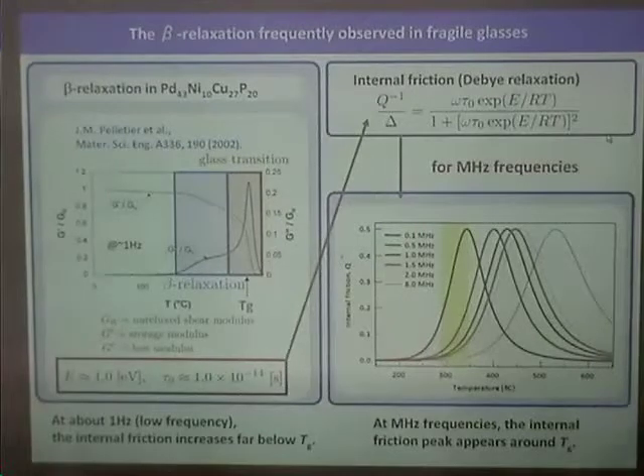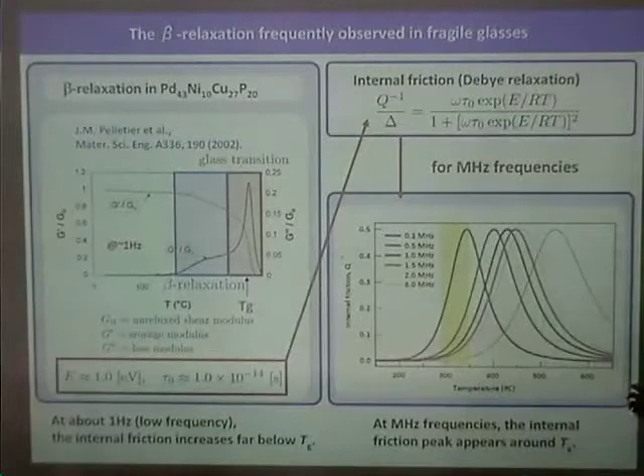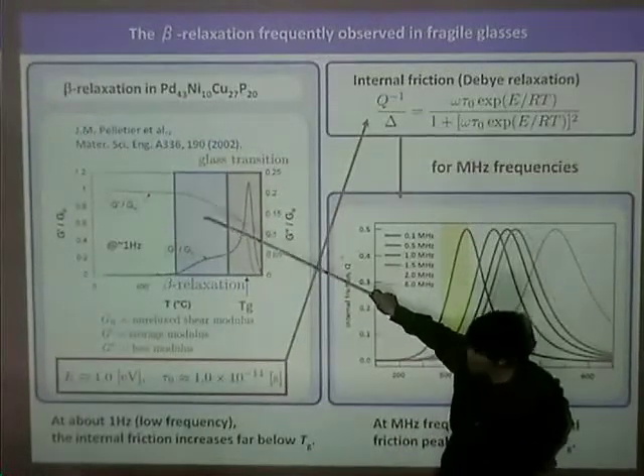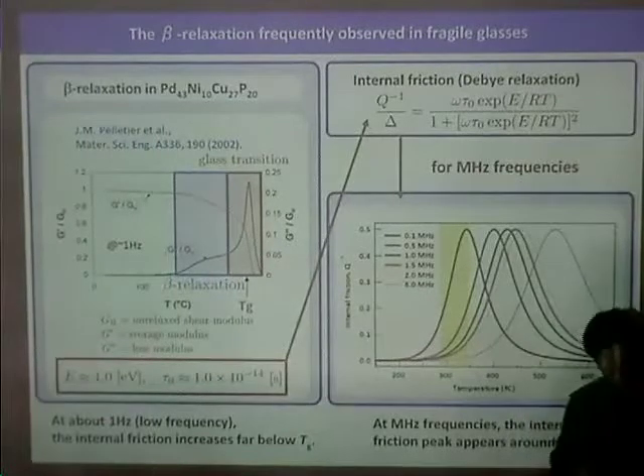What's special about megahertz frequencies for these atomic glasses? It seems fairly fast. Around the glass transition temperature, the atomic motion is very, very fast. If there is a region where the atom can move... Pelletier derived from his experiment the activation energy E and relaxation time. Is this an activation energy for one atom? Yes, one electron volt, one eV.